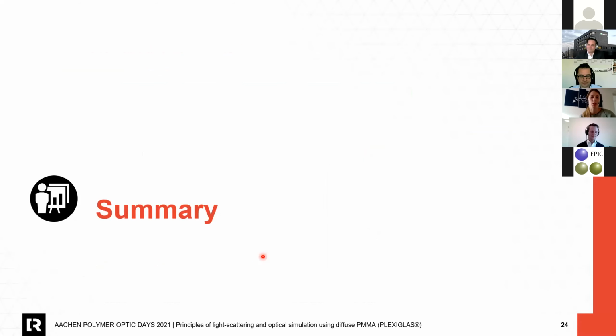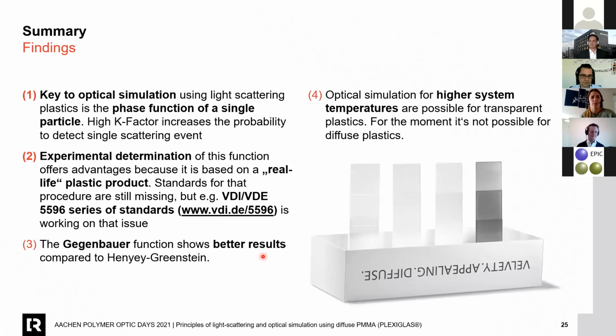Yes. Last but not least, a short summary in a few bullet points. At first, the key to optical simulation using light scattering plastics is the phase function of a single particle. So if you have a high K factor, the probability of single scattering is higher. The experimental determination of this function offers advantages because it is based on a real-life plastic product. Standards for that procedure are still missing, but we are working on this issue in the VDI VDE 5596 series of standards. The Gegenbauer function shows better results compared to the Henyey-Greenstein.